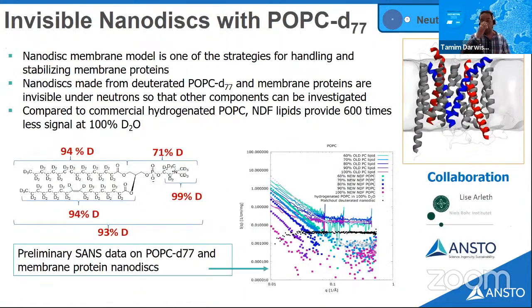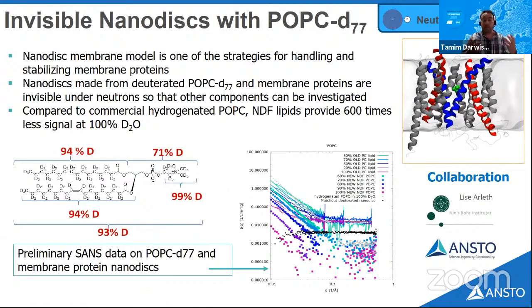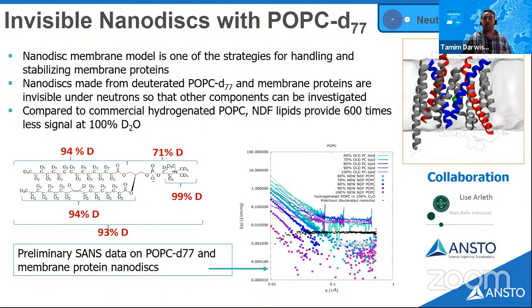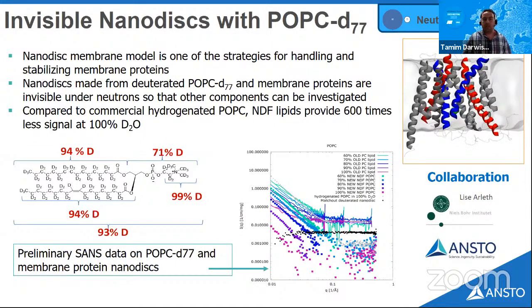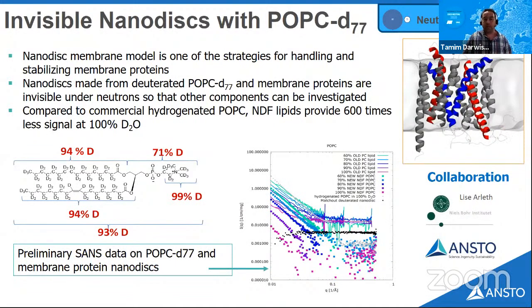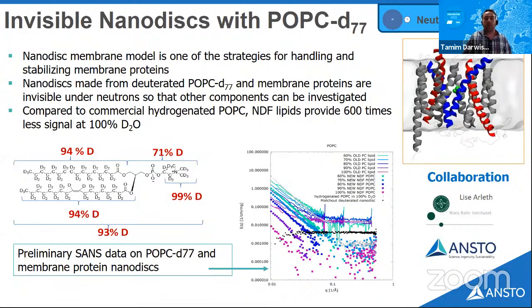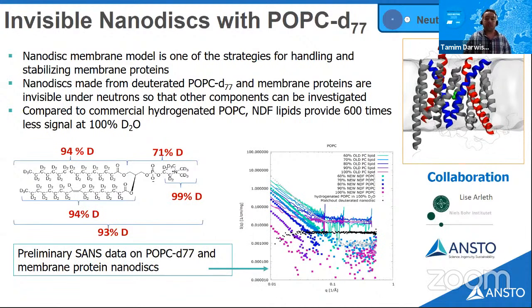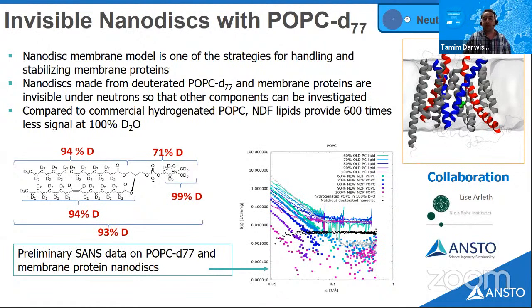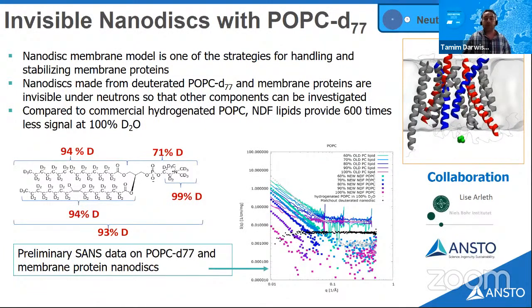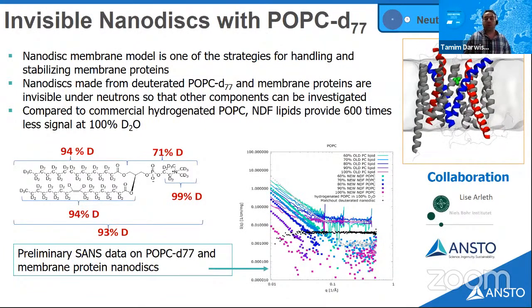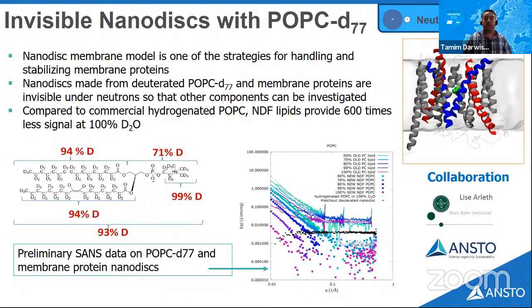The other thing is, because of the large quantities of oleic acid we produce, we can make large quantities of nanodisc lipids, like the ones here that we use with Lise Arleth from Copenhagen University. This is an invisible lipid for nanodisc studies, which has 600 times less signal in 100% D2O than the commercial hydrogenated POPC that you can find.